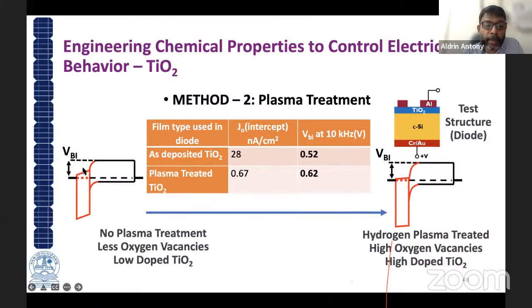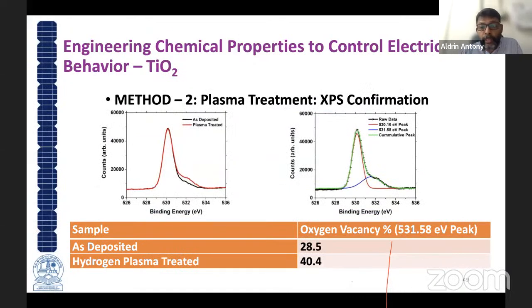So you could see by a hydrogen plasma treatment of this layer, you could increase the built-in potential, and that you could show it in the device. That is, this was an as-deposited device with a VBI of 0.52, a marginal increase up to 0.62. We could get it by a hydrogen plasma treatment. And this we could prove by XPS studies. This is a deposited film, and when we take the oxygen 1s peaks and deconvolute the peak, you could identify the oxygen vacancies at 532 is increasing. So with the hydrogen plasma treatment, the oxygen vacancy percentage is increasing from 28.5 to 40.4%.